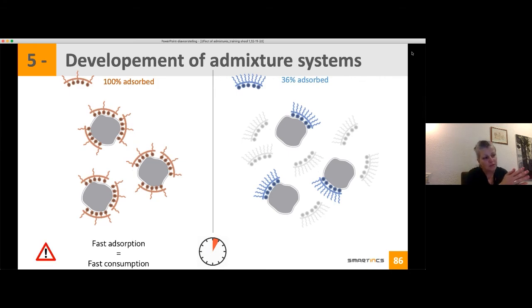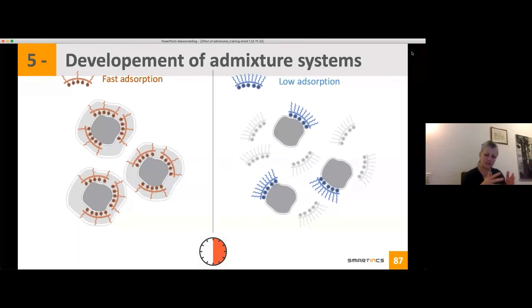Now, if you look in the case of the red one, you have a fast adsorption because everything is immediately adsorbed, but then it also means that it's consumed really fast. Because with time, you have this hydration layer that grows. It will also grow if you have your superplast at a point. And at a point, your superplast will be trapped in your hydration layer. So it means that at that time, you have loss of functionality because the hydration layer from two cement particles will get into contact and you don't have PCE anymore in your solution. So this is where you see a loss of functionality. And what you will see in your mix, you have loss of workability.